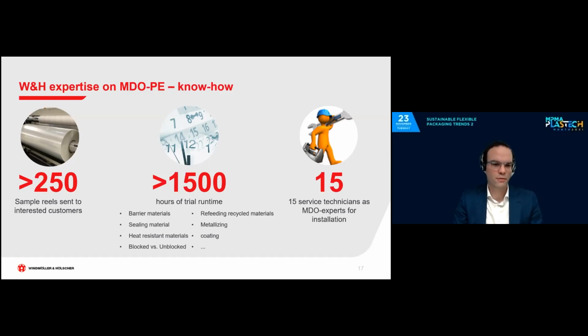And what have we tested in addition to this use case that we have shown you, this standard pouch? We have tested stretching barrier raw materials like polyamide nylon, EVOH. We have used different sealing and heat resistant layers. We have produced films in blocked and non-blocked structure, 1-up, 2-up, and saw challenges and solutions for both methods.